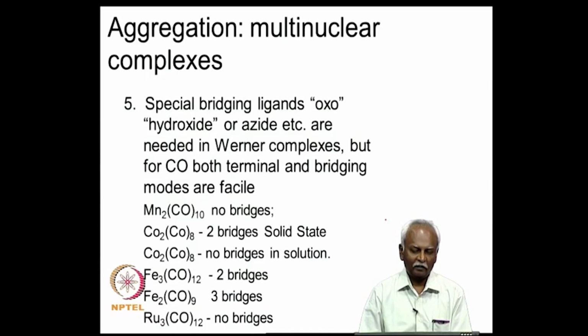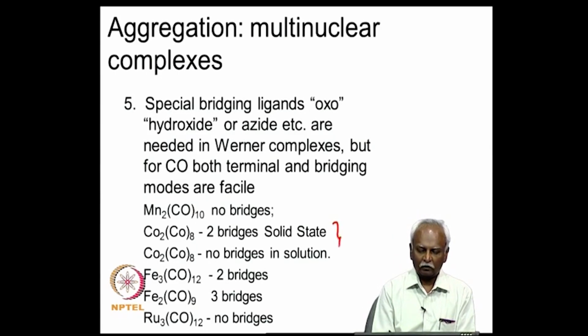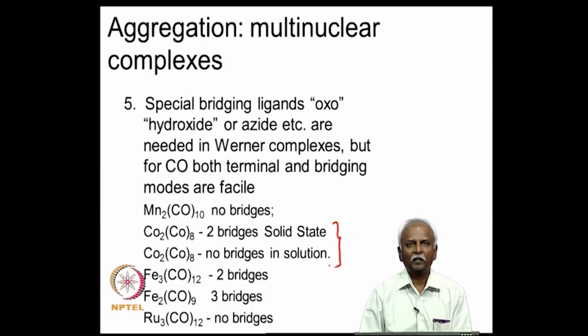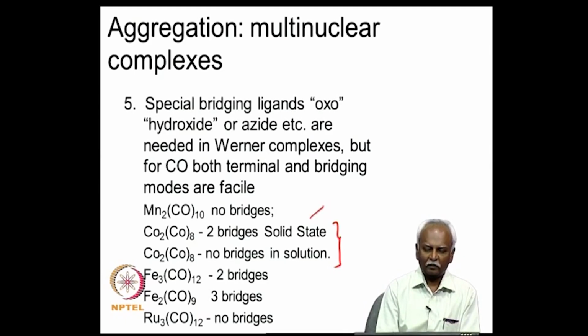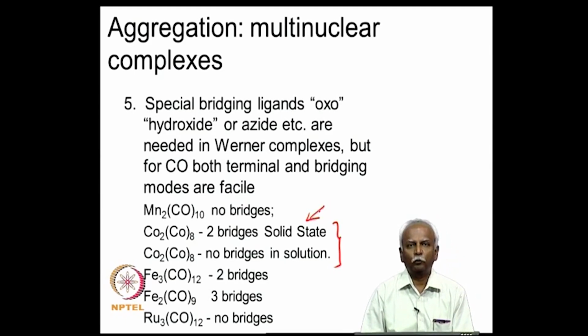And in one unique instance, at least in the case of dicobalt octacarbonyl, which I have pictured here, it has been noticed that both terminal and bridging modes of carbon monoxide are encountered in the complex. In the case of the solid state structure of Co2(CO)8, which I have mentioned here, it has two bridges. In the solution state, it has been noticed that there are no bridges in the dimeric species that is formed. So, it appears as if there is a very delicate balance between carbon monoxide being a bridging ligand or a terminal ligand. Both of the systems appear to be equally facile.